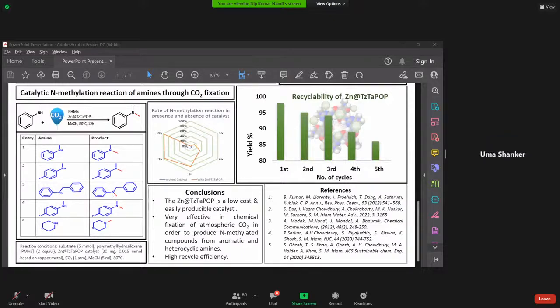Okay, Mr. Deep, tell me one thing. How are you sure that the total CO2 has been converted during the alkylation reaction? As we use CO2 balloons, we can measure the consumption from here. As the amount of air inside the balloon decreases, we can see that the CO2 inside the balloon was used up. And once we used it up, we again refueled the balloon with CO2.